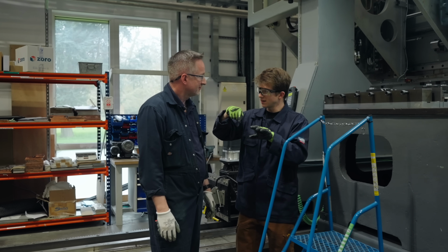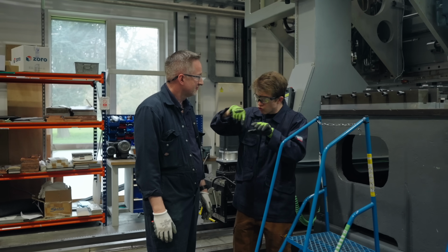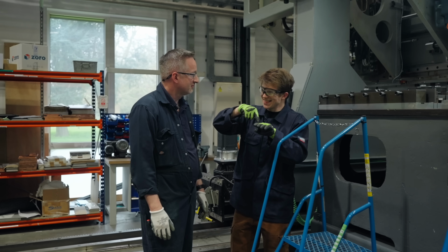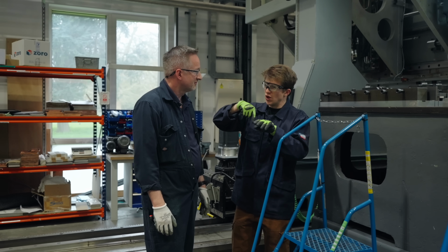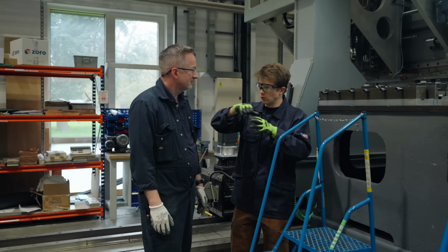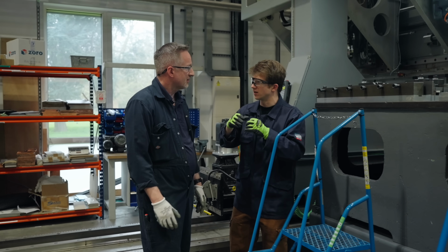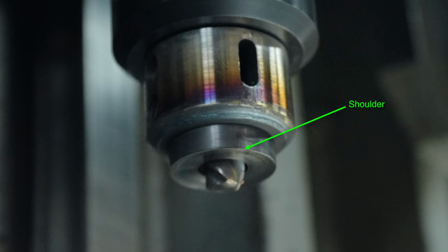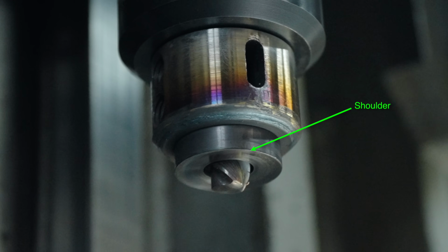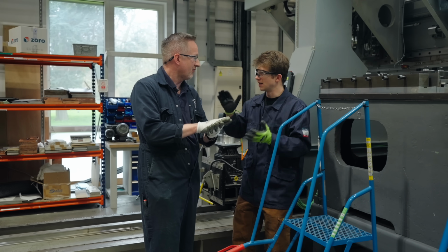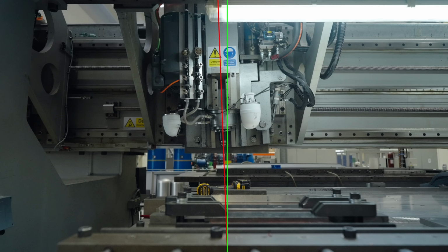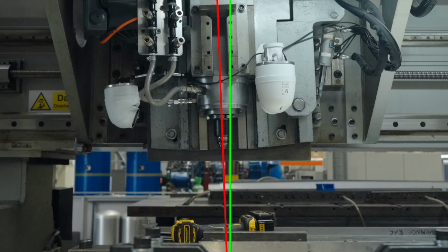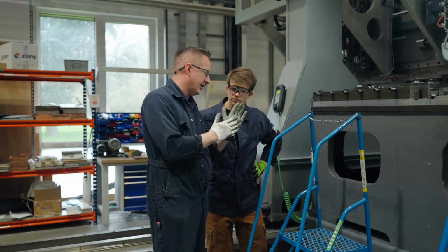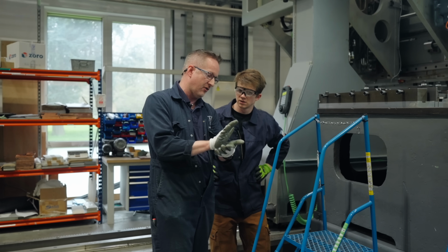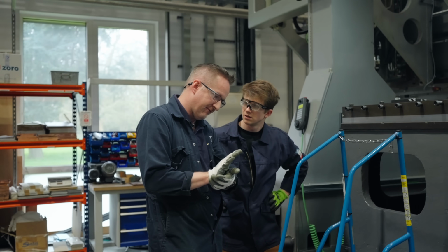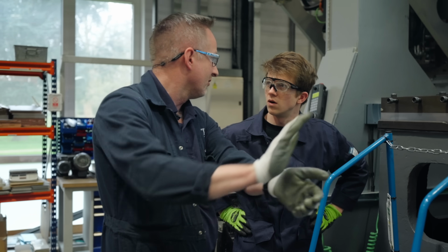That tool's going to be spinning, and the tool is going to be rubbing on the material, heating it up. In that hot state, it's plastic enough that it's then going to be just throwing it all over the place, stirring it together. And the shoulder is there to encapsulate the weld afterwards, so it doesn't just fly everywhere. You might notice that we've got a slight tilt on the head. They've got a little lean over there, right? Yeah, a little lean. And that gives us a forging action on the back end of the shoulder. It irons basically the weld when it's finished.